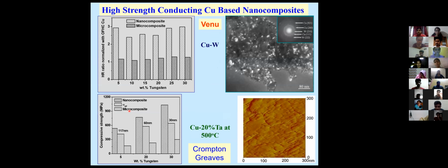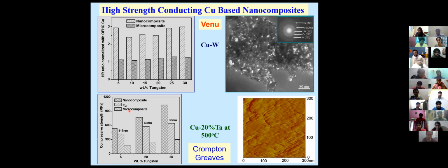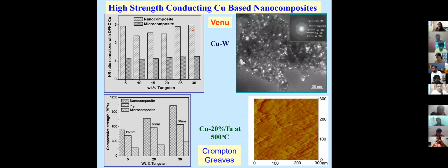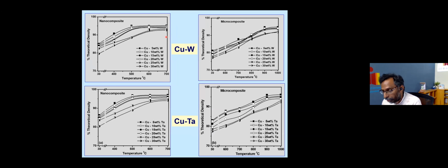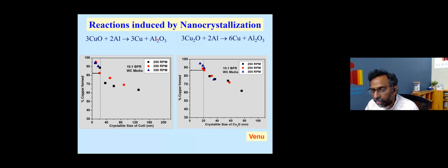We can also demonstrate this with materials which are usually used as electrical conductors, such as copper. Copper is a good conductor, but unfortunately copper is very soft. Can I make copper strong without losing the conductivity? Again, we demonstrated that if you make it nano copper and somehow ensure that the nano is retained, you can have almost 3 times the strength of regular copper without losing much conductivity. These are all very exciting things one can do. One can also demonstrate this in various other cases.